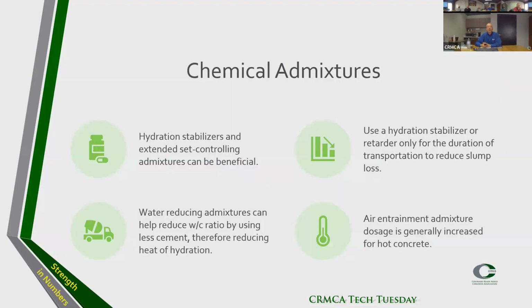Chemical admixtures. Something we suggest is to use a hydration stabilizer or extended set admixtures that can be beneficial for hot weather. Water reducing admixtures, they help reduce the water cement ratio. So you're gonna use less cement and you reduce the heat of hydration, you reduce the total temperature in the concrete.